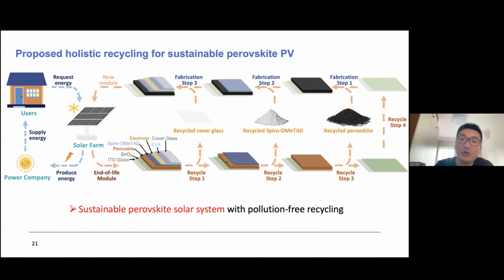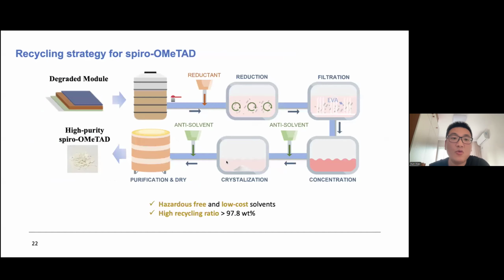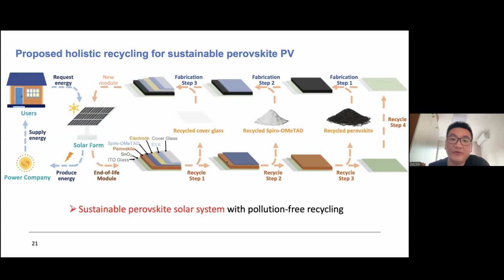Then we think only in this way can it be called a sustainable perovskite PV. So how do we achieve this? For the recycled cover glass, this is easy. We just use heat to soften the EVA, because the glass transition temperature for EVA is just around 120. So we use 150 degree C heating to soften the EVA and then mechanically detach the recycled cover glass.